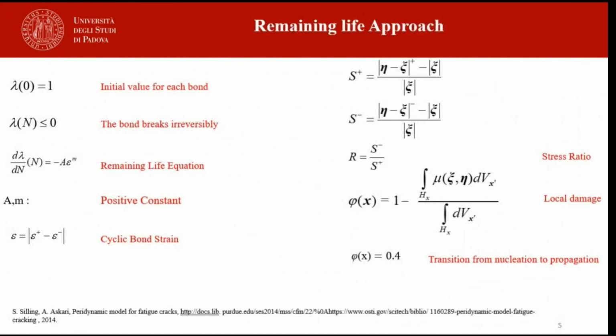Now let's look at the remaining life approach, which is used to describe how the peridynamic bond degrades over time. Each bond is characterized by a damage variable named remaining life, lambda, with an initial value. When the material undergoes cyclic loading, the bond gradually degrades, and when lambda is equal to or less than 0, the bond breaks irreversibly.